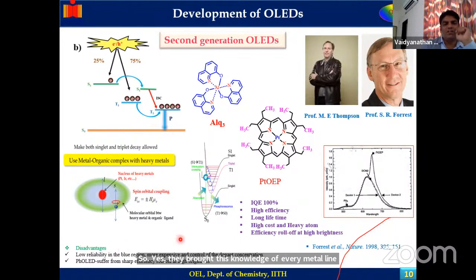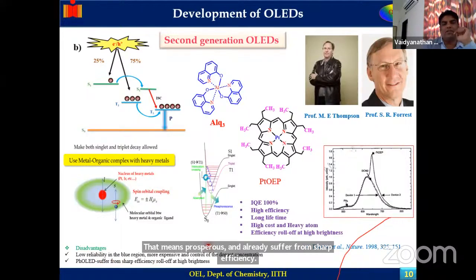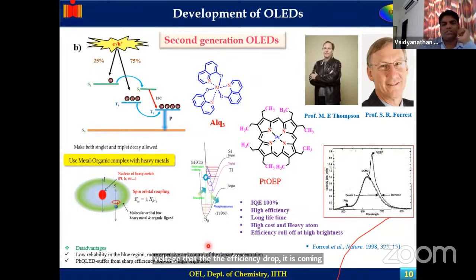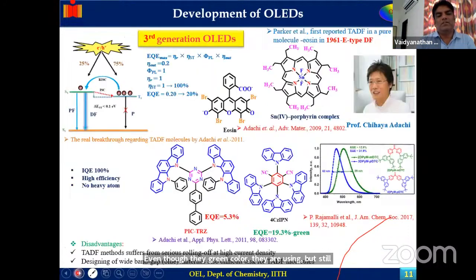The disadvantages are low reliability in the blue region, higher expense, and control of the dopant concentration. PhOLED, that means phosphorescence OLED, suffers from sharp efficiency roll-off at high brightness. When you increase the voltage, the efficiency drops. Also, the heavy metal ion is very expensive. That is also one of the key reasons this cannot be used for practical application. Even though green is being used, blue and red still need some discovery.